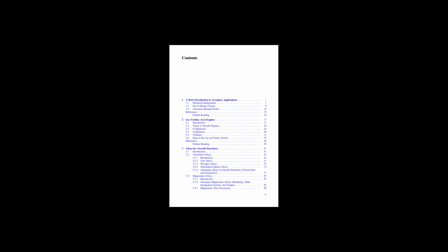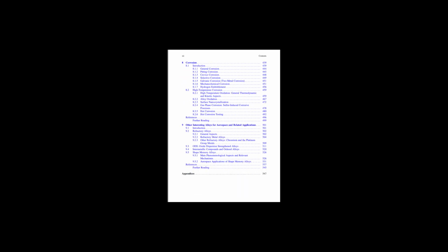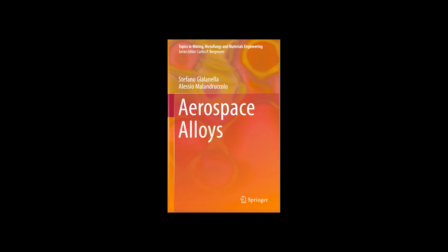Right, PVD, physical vapor deposition, and CVD, chemical vapor deposition. These are more about depositing the coating material atom by atom, or molecule by molecule, from a vapor phase onto the surface. They can produce very dense, uniform coatings. There was also pack cementation for aluminum coatings. Yes, pack cementation, particularly aluminizing, is an older but still used diffusion process. You basically bury the parts in a powder mixture containing aluminum powder, an activator, like a halide salt, and an inert filler.